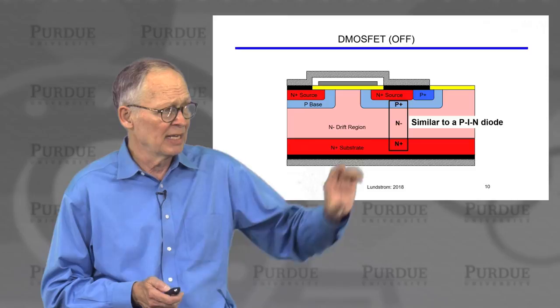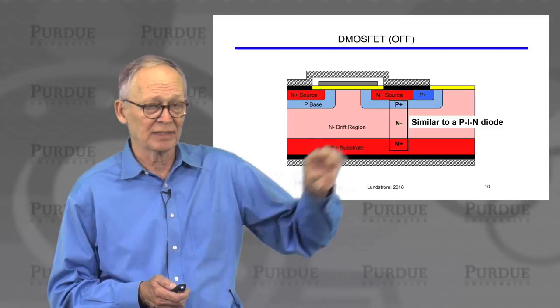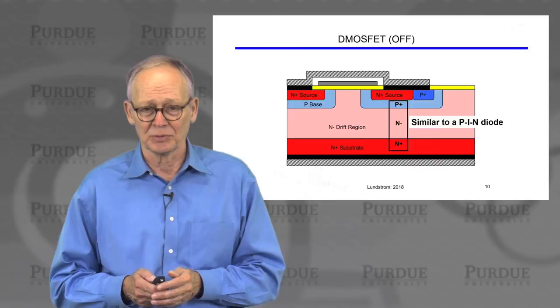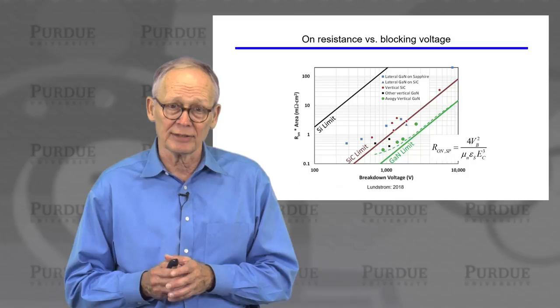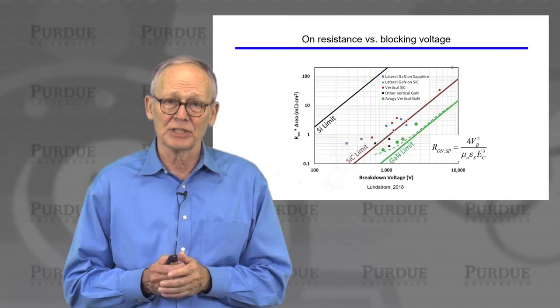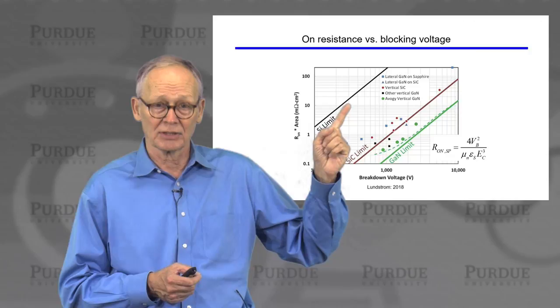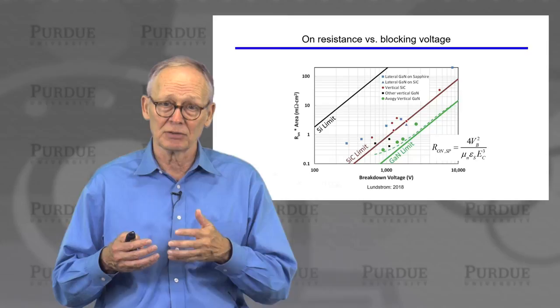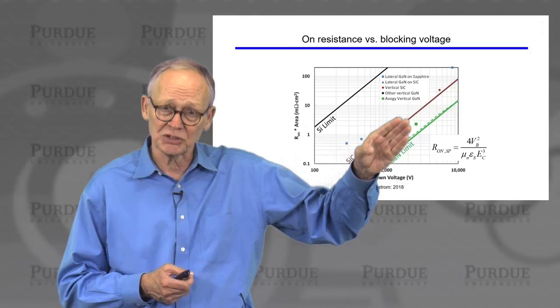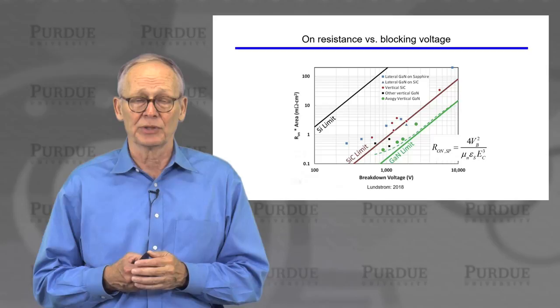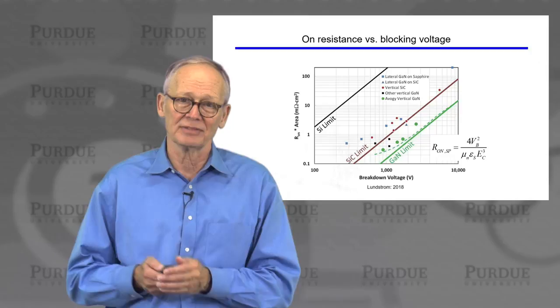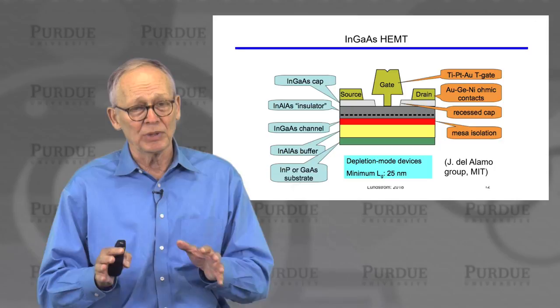The breakdown voltage — we need not only a lot of current and low resistance, but also high breakdown voltage. The breakdown voltage is determined across the P-N junction, so we'd like to make the doping as light as possible, make the electric fields as small as possible, and make the thickness of the wafer as large as possible. There is a fundamental tradeoff between the on resistance, which we want to be low, and the breakdown voltage Vb, which we want to be high. A wider band gap material like silicon carbide, which has a higher field for breakdown, will allow us to push to much higher voltages. Gallium nitride, which has an even higher critical field, would allow us to approach 10,000 volt operation for these power MOSFET devices.